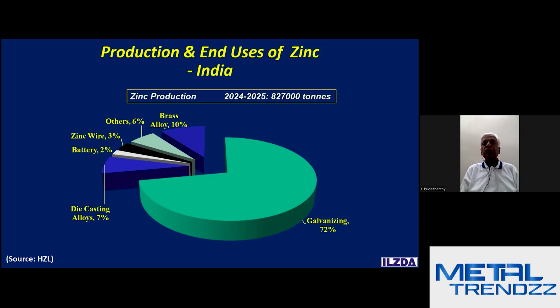In very corrosive locations like industrial or marine atmosphere, the life will come down. Therefore, in such location where the life will come down, you have to deposit a thicker coating. The important point I'm driving home is the service life of the galvanized product depends on the coating weight applied. You double the coating, you will get double the life. Triple the coating, triple the life. Therefore, this is an important factor.